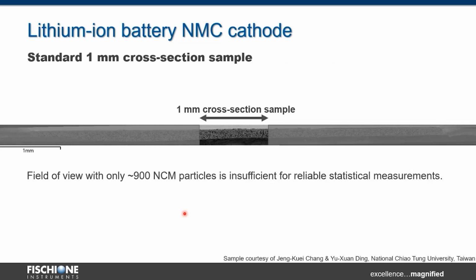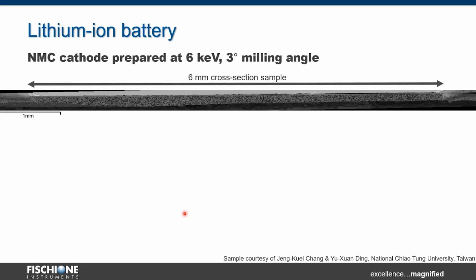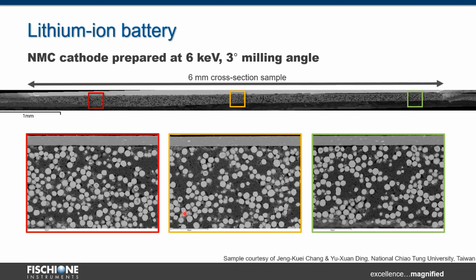And if you compare that sample preparation to a standard 1 millimeter cross-section sample, as you can see here, you can count maybe 900 NMC particles, which provides limited statistical confidence in your analysis. So, of course, the sample preparation, as you already saw in the titanium example, the sample is uniform, the cross-section is uniform.